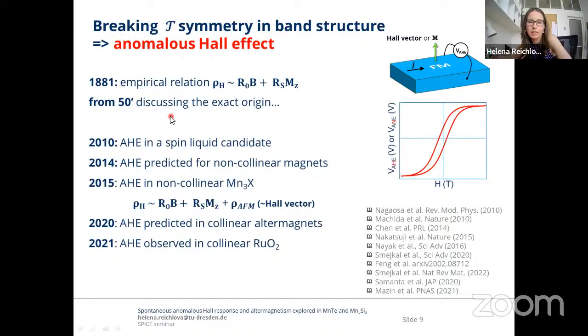And this empirical relation was then discussed for tens of years to find the exact origin. One of the important results of this interesting discussion was that there are other contributions to the anomalous Hall effect, which are sort of intrinsic contributions arising from the character of the band structure itself of a perfect crystal. And what is important for us is that it does not scale with magnetization. It does not imply that the net magnetization needs to be present. And the anomalous Hall effect was consequently observed, for example, in a spin liquid candidate. In 2014, it was predicted for non-collinear magnets.